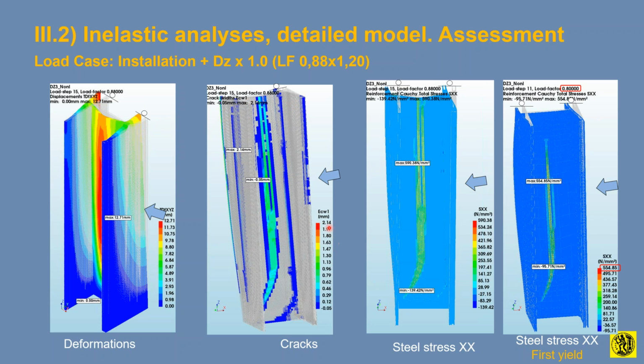Now we see that the actual crack pattern, again, concurrent with the installation phase, changes completely, and we have a full zipper crack all the way in the middle of this. So we crack not only in the supports, but also in the middle out of plane here. And now we see the stresses. The stresses are actually developing yield at this load case here, higher than yield actually, and a little bit higher in the entire height.